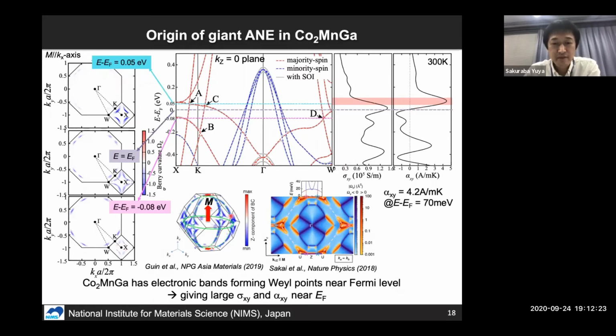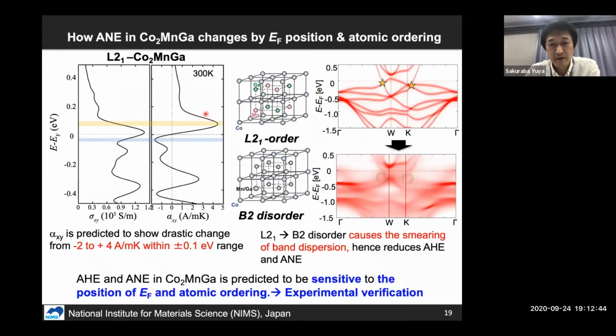These two studies pointed out that the formation of Weyl points near the Fermi level is the reason for the large sigma xy and alpha xy near the Fermi level. And okay, this kind of theoretical prediction gives us the motivation to work on several things. Because this alpha xy must drastically change around the Fermi level, it is very interesting to study how the position of the Fermi level changes the magnitude and sign of alpha xy and the power of the anomalous Nernst effect. So it is very interesting to tune the position of the Fermi level.